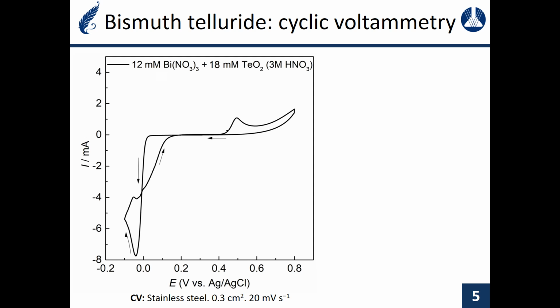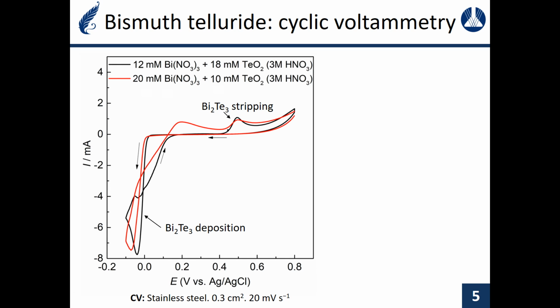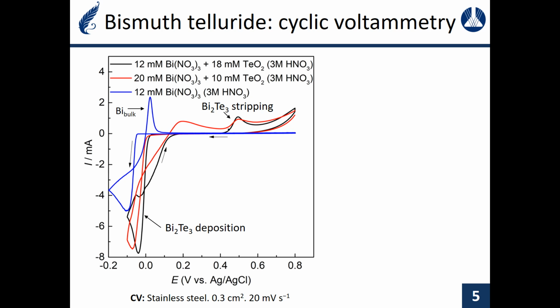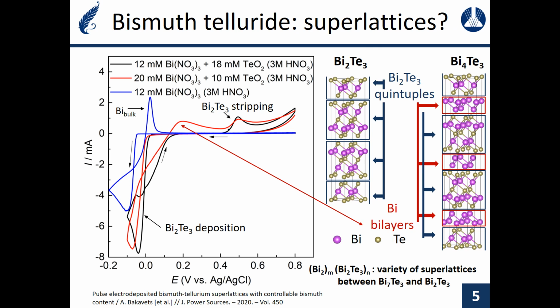This slide shows cyclic voltammograms for the electrodeposition of bismuth telluride from the solutions of its precursors and the subsequent anodic oxidation of the electrodeposits. The film deposition is the reduction process, and it proceeds at negative potentials. Bi2Te3 oxidation proceeds at more positive potentials. With increase in the concentration of bismuth cations in the electrolyte used for electrodeposition, an additional process is observed in the anodic scan. The potential corresponding to this process is intermediate between the oxidation of bulk bismuth telluride and metallic bismuth. This process corresponds to the selective oxidation of the interlayered bismuth in Bi2Te3-Bi superlattices, and the thorough proof of this was presented in our article in the Journal of Power Sources.